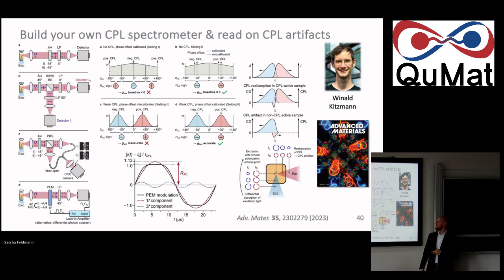And then it gets a bit nerdier if you're really interested in things like how the photoelastic modulator modulates a response in a typical lock-in based technique. You have to be wary about the non-sinusoidal response of this PEM modulation. So you have to think about actually correcting for it, for which you would need an n-order Bessel function of the first kind. But if you do not, you actually miss out on the 10% or so. It's really not that trivial to do right. Phase offset calibration is probably something most people will never have even looked into.